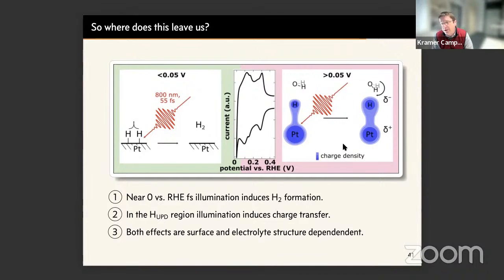So we do a bunch of work on hydrogen evolution and some on the OER as well. And as you say, hydrogen evolution is not so complicated, although I think we struggle to understand issues like the underpinnings of the pH dependence or electrolyte effects on hydrogen evolution rates. The OER is obviously a lot more complicated, but most of the interesting intermediates, at least from a vibrational perspective, are at quite long wavelengths, like this peroxo species, which makes the experiment a little more challenging. But all of this kind of small carbon molecule chemistry is pretty straightforward to probe in this probing scheme.